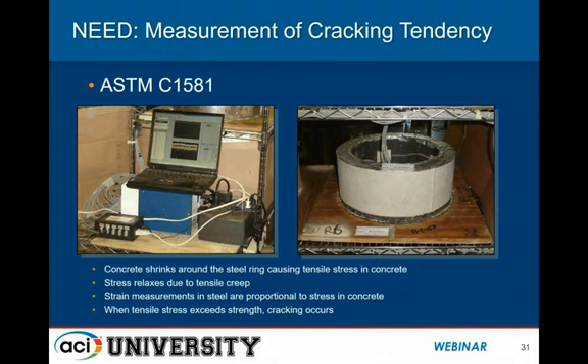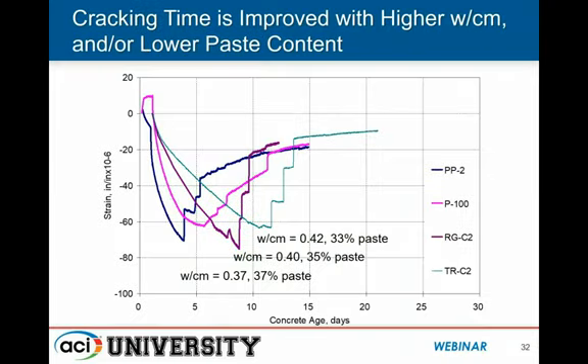So to give you a little bit more feel for this test, again, we said it's this concrete donut. We instrument the inside of the steel pipe with strain gauges, and then we monitor the strains on a computer, and that tells us when the cracks are going to occur. It also allows us to compute and monitor the stresses in the concrete over time and get a rough idea for how quickly the tensile stresses develop. So again, I think this is a critical test that gives us a lot of insight into what types of concretes are beneficial from a cracking standpoint.